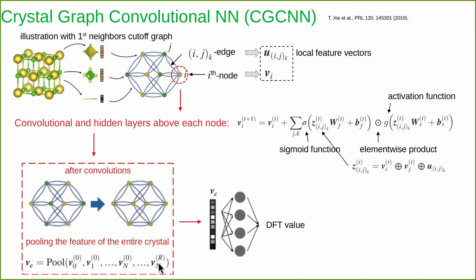And that's what you can see here. In each layer you have different vectors depending on the size, and how many sites you have depending on the cutoff radii you are using, which is a hyperparameter. Then you pool together with a simple sum function into one single crystal-representing feature vector. Then again, you use a simple neural network with some hidden layers, the number of hidden layers being again a hyperparameter, and you can train the DFT value. The DFT value can be bulk modulus, shear modulus, or any type of parameter which we have stored in the database, and that includes also the formation energy or the mixing entropy.